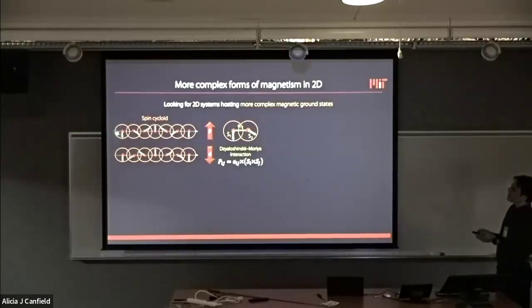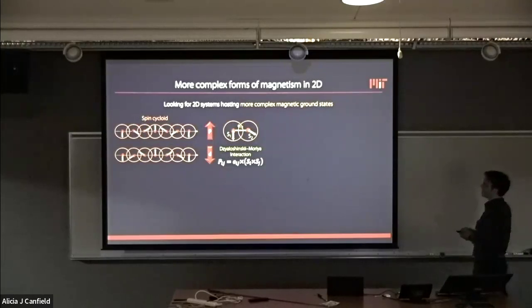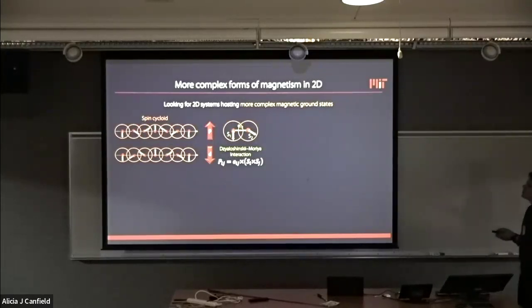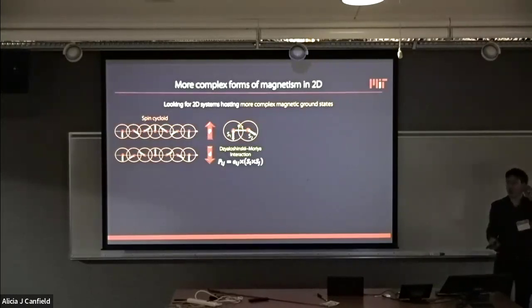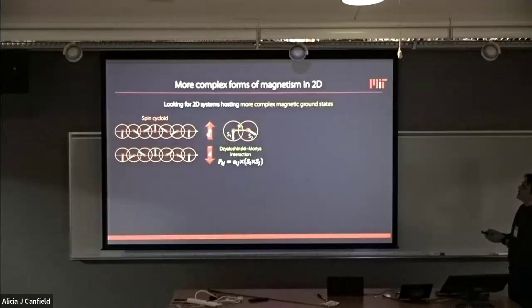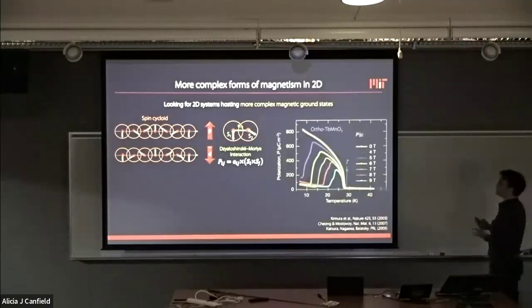In a spin cycloid, the spins rotate in a plane which is parallel to the propagation axis. Through the Dzyaloshinskii-Moriya interaction and the Katsura-Nagaosa-Balatsky model for the spin currents, you can actually realize an electrical polarization from the local inversion symmetry breaking that happens between pairs of non-collinear spins. So pairs of non-collinear spins produce a polarization, and that polarization can be switched if you switch the handedness of the cycloid. And this was beautifully demonstrated.